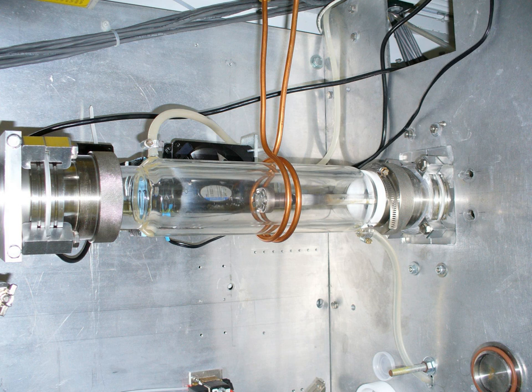Diborane B2H6 is used as the boron source. Magnesium boride film starts to grow when the boron precursor gas B2H6 is introduced into the reactor chamber. The growth rate of the magnesium boride film is controlled by the flow rate of B2H6-H2 mixture. The film growth stops when the boron precursor gas is switched off.